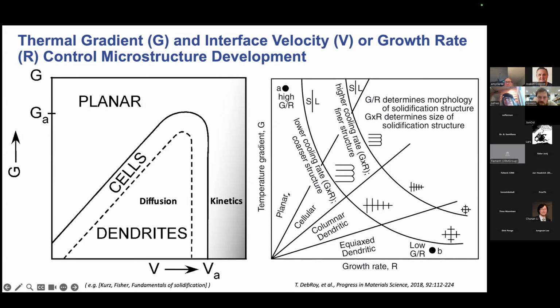And not only do we have the planar, cellular, dendritic regimes broken out, we also have a distinction between the columnar and the equiaxed. So this is called the columnar to equiaxed transition, or CET. This is where we go from elongated columnar grains that might have anisotropic properties to more equiaxed, refined grains that you would expect to have more isotropic properties. So the CET is important in the context of additive manufacturing, especially.